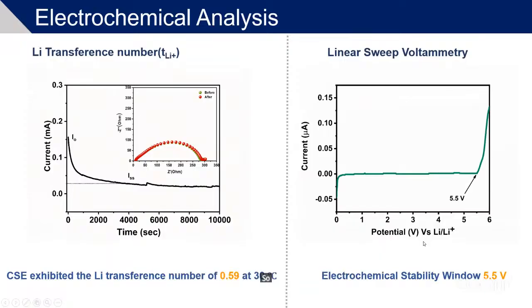Further, we have studied the transference number, and the value of the transference number is around 0.59. And this is the linear sweep voltammetry graph, the electrochemical stability window, which is around 5.5 volt, whereas in liquid electrolyte it is only 4.2. So this is the advantage of the solid polymer electrolyte. That means the electrochemical stability window value increases.